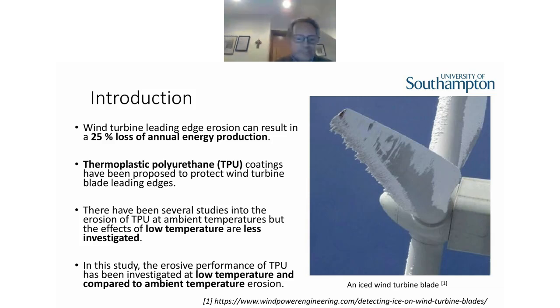So why are we interested in cold erosion? Clearly, damage to the leading edge can lead to quite dramatic drops in the efficiency of energy extraction from wind, up to about 25%. The technology that people are turning to is thermoplastic polyurethane coatings, and there's a variety that you can choose from. We found little in the public domain that looked at the effects of temperature, particularly low temperatures. So that's really what we wanted to do in this study. We were trying to compare ambient room temperature studies with lower temperature to see what the resulting erosion and micromechanical properties might be of these systems.